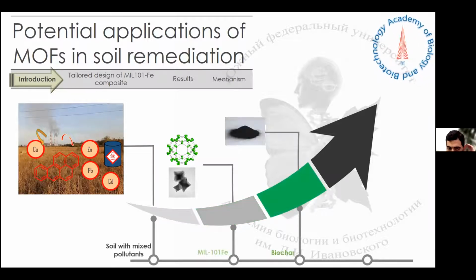Then we were afraid that if we use the metal organic framework directly in the soil, the pollutant is not distributed evenly, and there is less chance for the metal organic framework to contact the pollutant. We were also thinking about the price of the metal organic framework. So we put these criteria together and decided to composite our material with biochar to reduce the cost and also take advantage of the synergistic effect between biochar and metal organic framework.